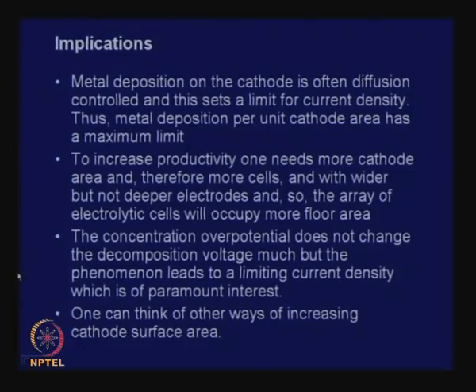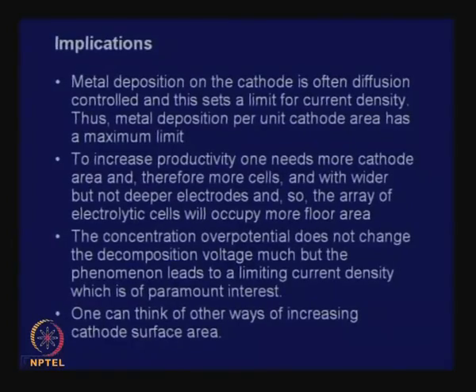So, let us summarize the implications now. Implications are that metal deposition on cathode is often diffusion controlled, and this sets a limit for the current density. Thus, metal deposition per unit cathode area has a maximum limit, and that will correspond to 10 to the 5 amperes per meter square. You can calculate how much metal deposition there is according to Faraday's law, taking into account the equivalent weight. Now, to increase productivity in a cell, one needs more cathode area.